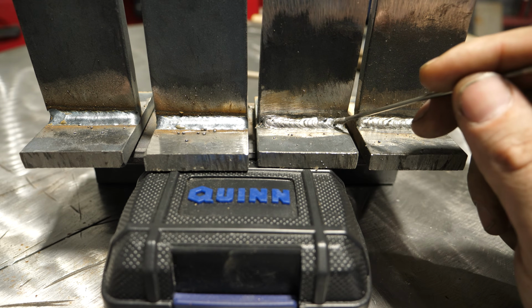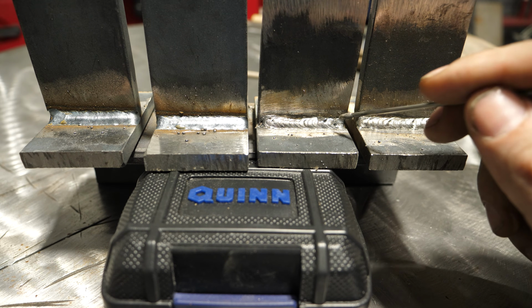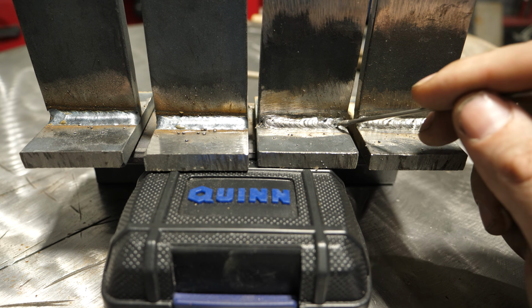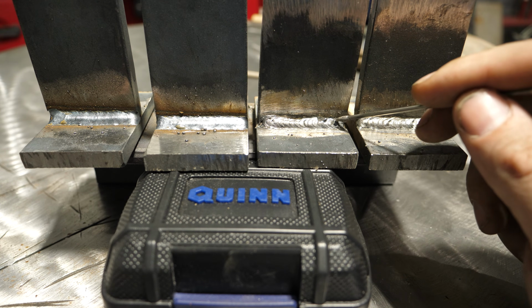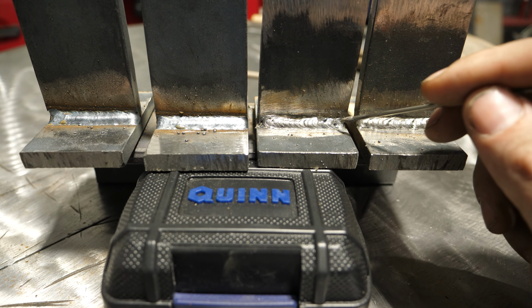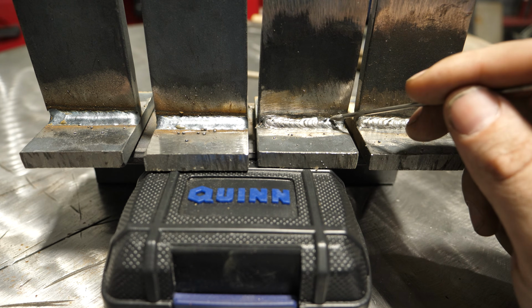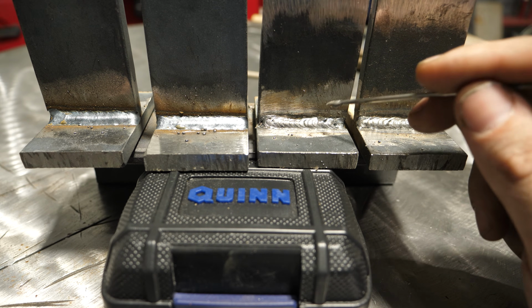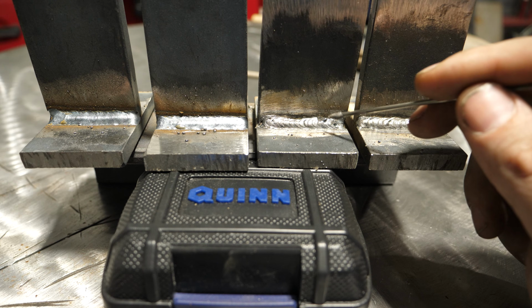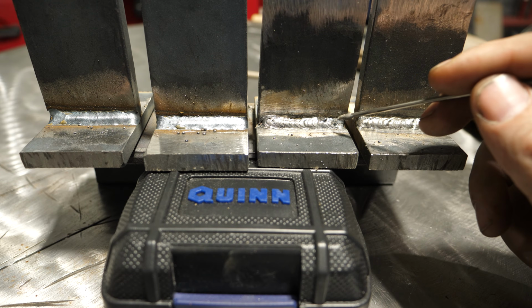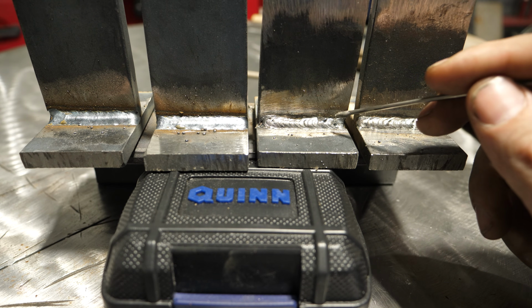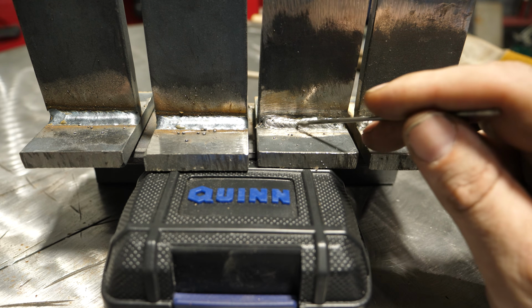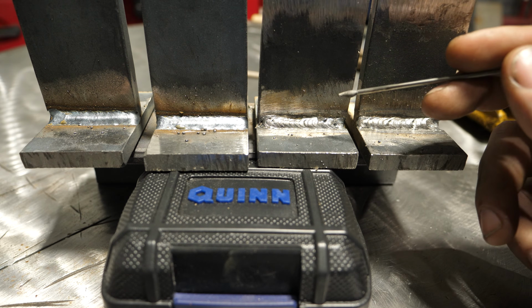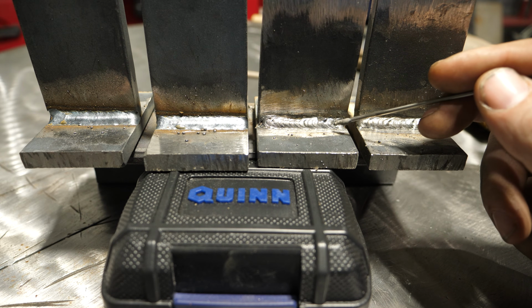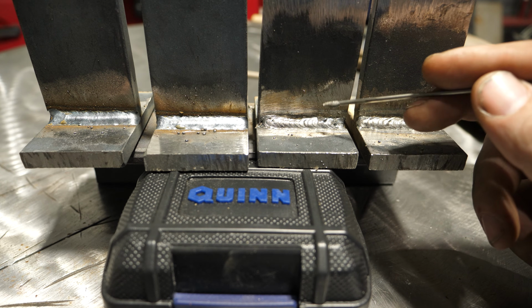And I think the issue is that 035 flux core cannot handle enough amperage, because remember, it's a hollow thin-walled tube, enough amperage to carry enough heat on this thick a plate. And when you crank it up, you basically melt the wire off in an undesirable fashion before it even hits where it should. And long story short, you have issues with porosity and whatnot.